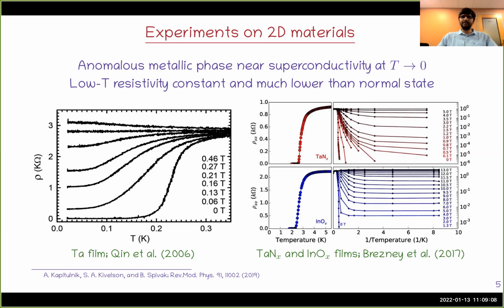Similarly, in this second example, it's a similar experiment where you have resistivity versus temperature, or in this case inverse temperature, for two different films. And you again see this saturation behavior at a very low value of resistivity.